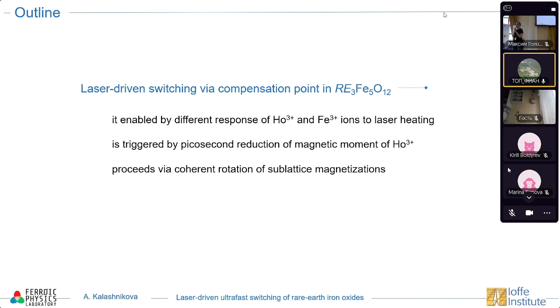And what's the dependence of temperature reduction with time? So how does it relax? This is a much slower process. Typically, it takes microseconds or milliseconds. Well, this is kind of a disadvantage of this process because when we, for example, trigger this ultrafast spin orientation transition, afterwards, after these milliseconds, the material goes back, unfortunately. But for this switching via compensation point, if we somehow find a way to remove the field, then in principle, if we have switching, it will stay there. Okay, thank you very much.